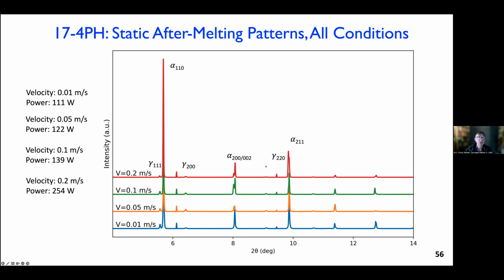And what I'm going to focus on in these diffraction patterns is one particular peak. So you see 4 different cooling rates, from quite low to something more like what you would use in printing. And look at this individual peak here. It's the 200 reflection for the BCC. And you notice that there is a single peak at the very low cooling rate, but it's clearly splitting when you get up here.